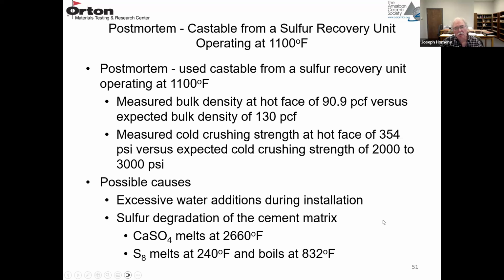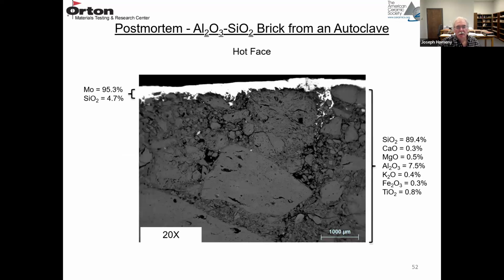So this material is degrading because of the sulfur that it picks up. And I put one more example here of a chemical type vessel. And this is an autoclave lined with aluminosilica brick. So this is the hot face of this refractory in the autoclave. And this is a reaction where they're extracting molybdenum metal, MO, from an ore.